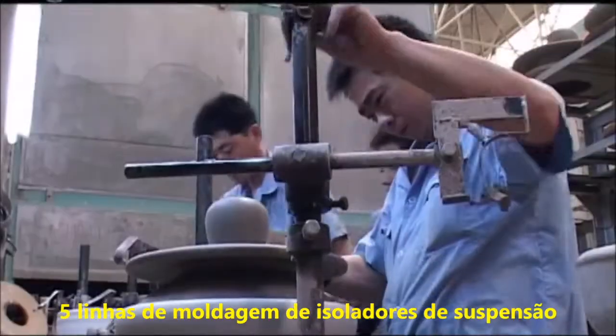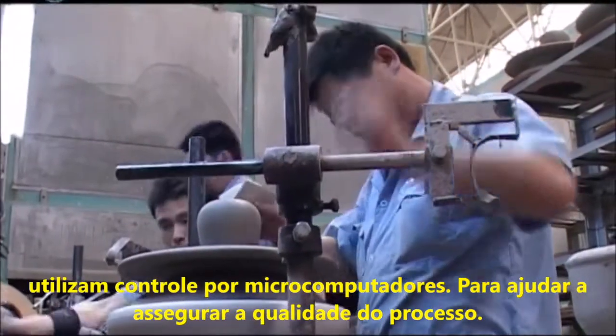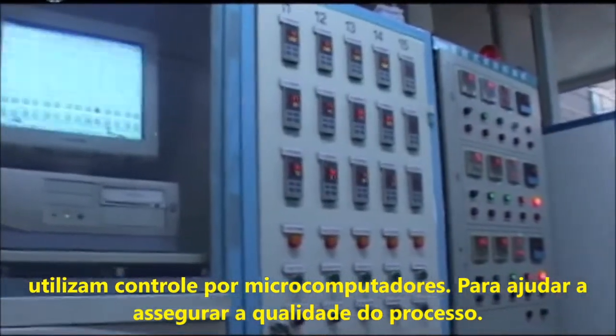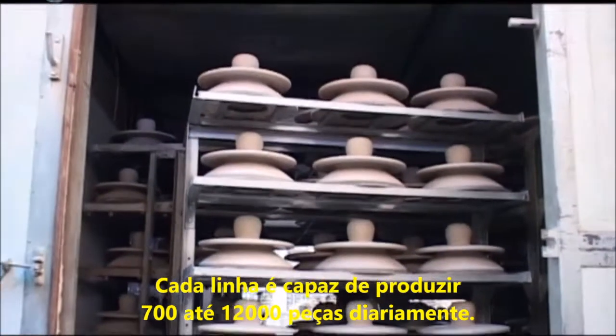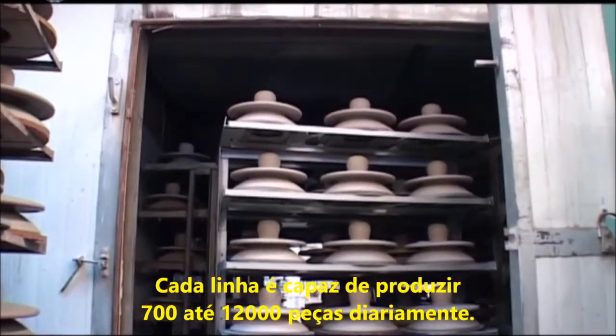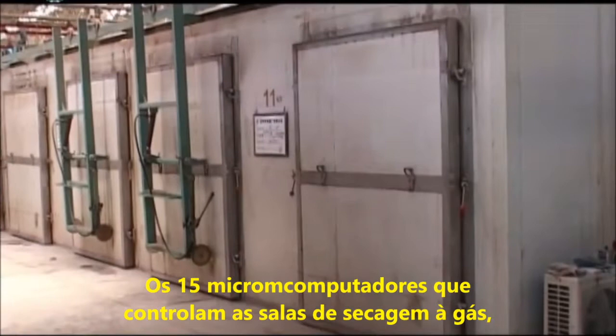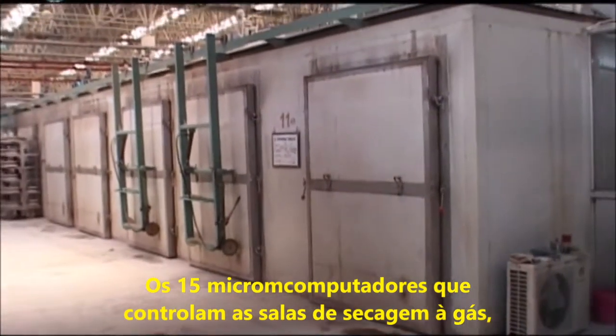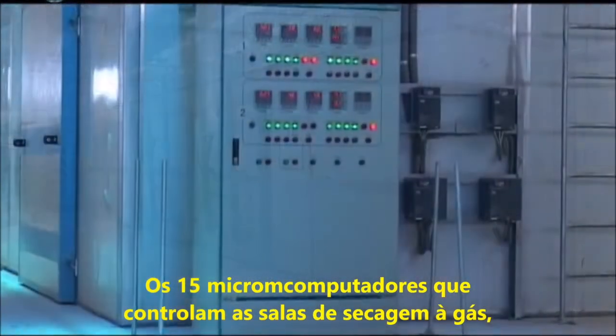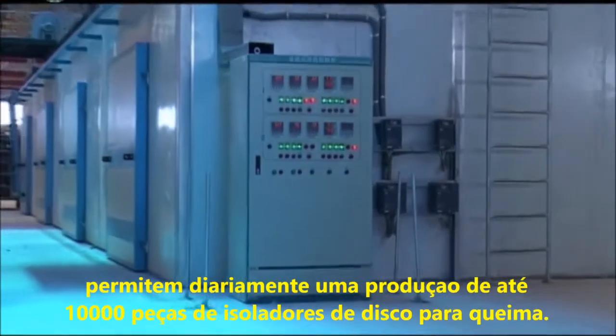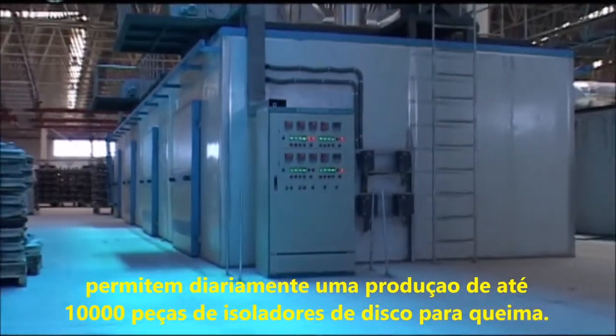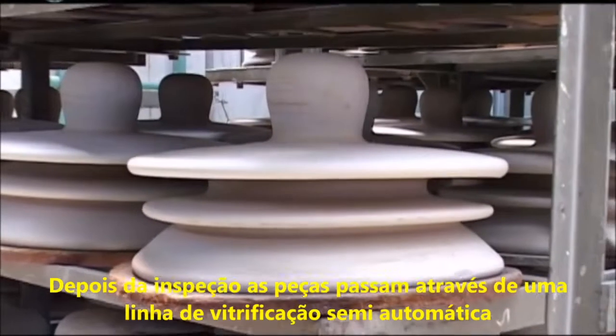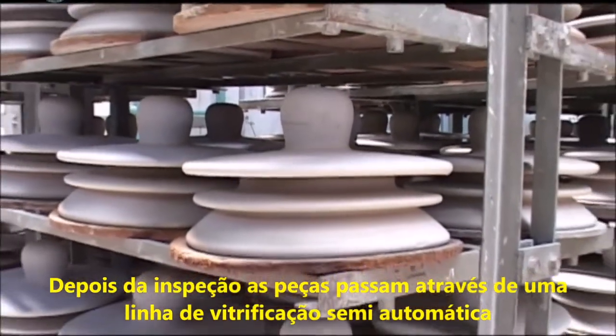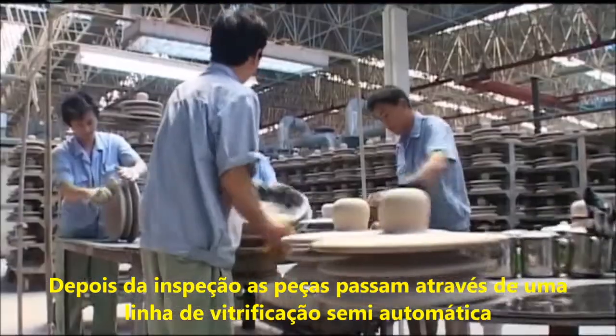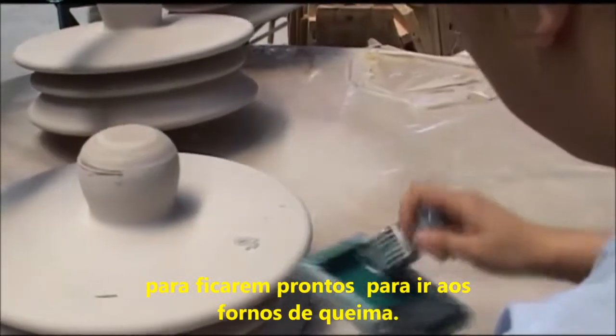5 suspension molding lines utilize microcomputer control to help assure process quality. Each line is capable of producing 700 to 12,000 pieces daily. 9 540-square-foot and 6 320-square-foot microcomputer-controlled gas drying rooms allow daily output of blanks to reach 10,000 pieces. After inspection, the blanks move through a semi-automatic glazing line in preparation for processing in the kilns.